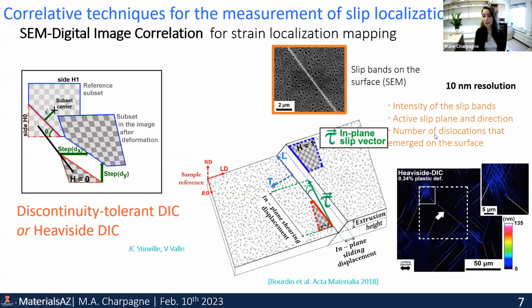So from this, we can actually back out physics-based information that really represents the reality of what's going on in those materials, meaning the intensity of the slip band. We can identify the active slip plane, but also the slip direction, and we can even back out the number of dislocations that contributed to the formation of that slip band. So this is now a very powerful technique that we use on a routine basis, because you can probe very large areas with it, up to several millimeters, and it doesn't take that long. So it's very mature and robust right now.